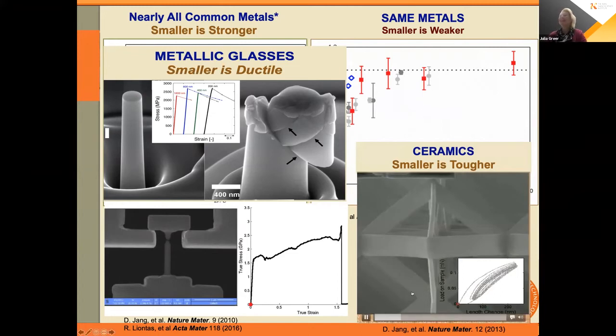So the movie is supposed to be playing and deforming this. And what you would see is that each individual beam is bending and it's made out of a very brittle ceramic, titanium nitride, and it's able to deform over multiple cycles without failure, even when the tensile stress is in excess of 1.5 gigapascals. Ceramics are not supposed to stay intact when you apply that much of tensile stress to them. So the takeaway message here is this.